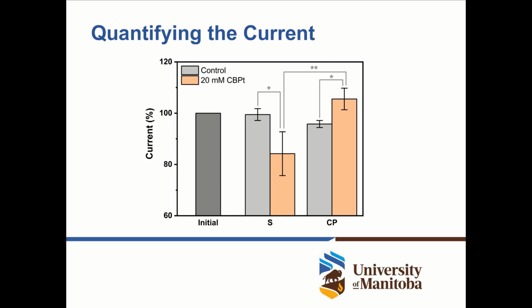Now we look at our control cells, the susceptible and resistant cells, which do not significantly differ without exposing them to carboplatin, because their intrinsic glutathione ratio seems to be very similar. However, when we expose them to carboplatin, we see that the current values for the resistant cells significantly increase, with a confidence interval of 99%. And in the susceptible cells, it decreases. This is one of the very first quantifications of these responses to the exposure of a chemotherapeutic.